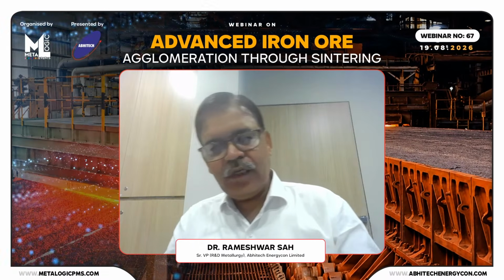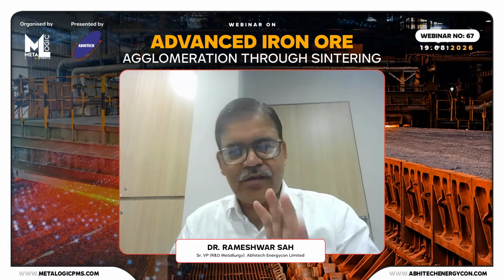So far as the siliceous ores are concerned, where the silica is high, it is also detrimental, but it has less impact than the alumina. But silica even to the level of 5 to 6, 7% is, I think, acceptable, because sometimes by maintaining the basicity it helps in making the slag bond formations. So a little higher silica could be acceptable, but more alumina will not be acceptable. This low grade ore has to undergo beneficiation and upgrade to the level where preferably the alumina could be brought below 3%, and silica could be in the 5 to 6% range.